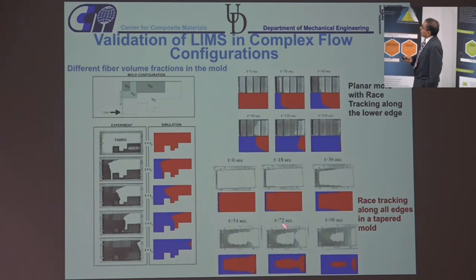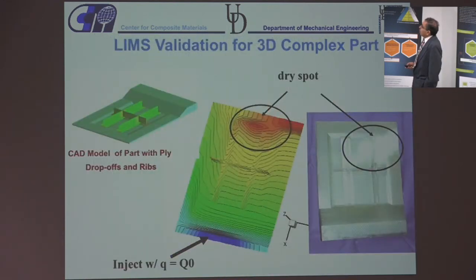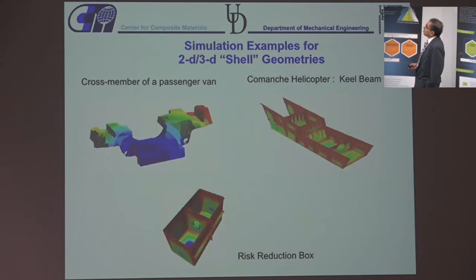Here you have race tracking along both the sides. So we've done many of these validations, and this is for a 3D part which had ribs and ply drop-offs, and the resin to come at the end was over here. So you would get a dry spot, and then again in our experiment we were able to predict that. Again, this one was a 6-foot by 3-foot part, so not a small part on which we did validation.